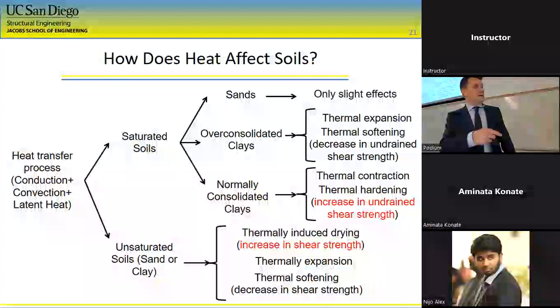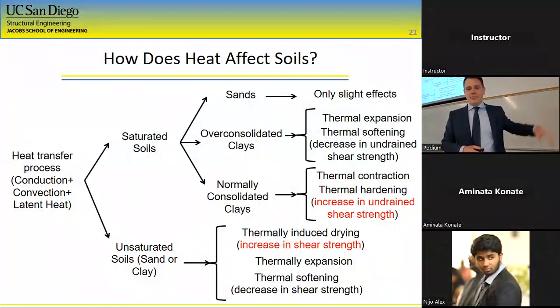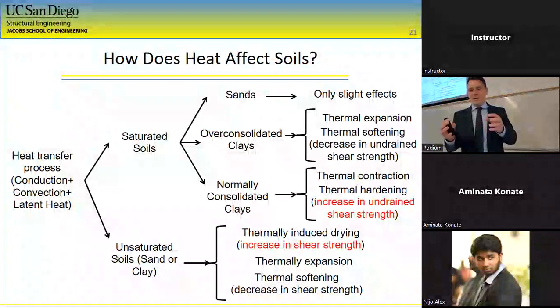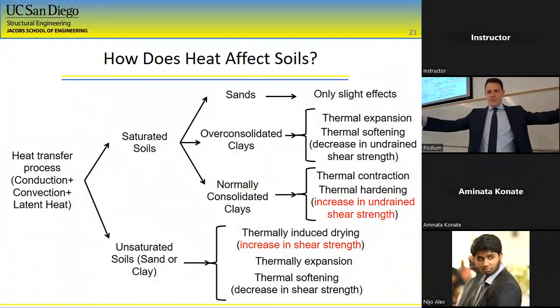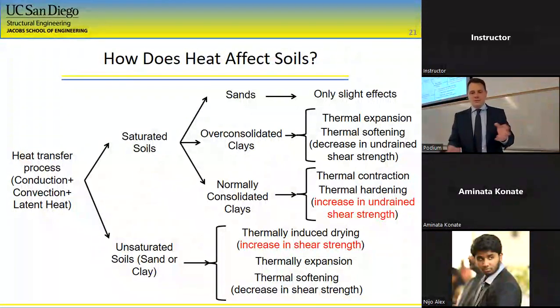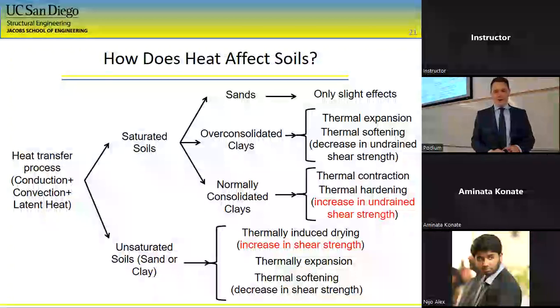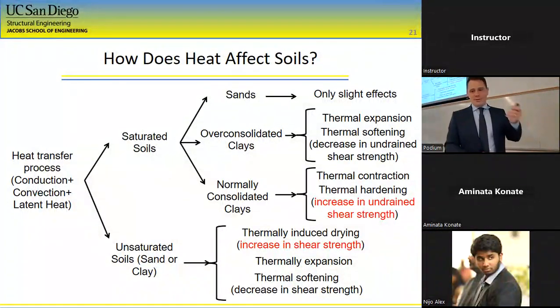Normally consolidated clays, like the soft clays that you have off the coast of the Gulf of Mexico here, will actually contract when you heat them. And it's because the water expands more than the solid particles. You have a thermal pressurization, and the pressurized water flows away and you contract. So it's like a negative Poisson's ratio material, but it doesn't have anything to do with the Poisson's ratio. It's just a weird material that when you heat it, it gets smaller. And then unsaturated materials, you also have this thermally induced drying. The water wants to go from high energy to low energy, so it's going to flow away from the heat source. And you have thermal expansion.